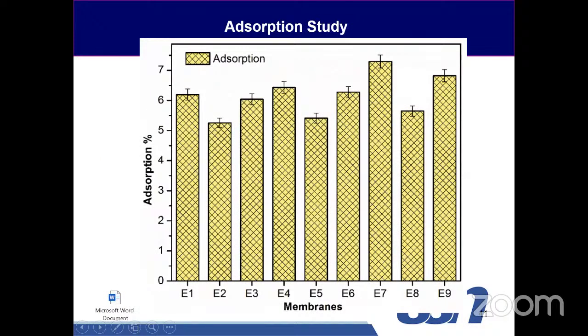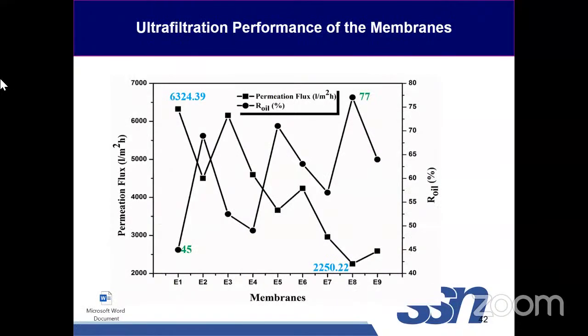Later on, we checked the ultrafiltration property of the membrane using an oil-water separation technique, where we found out E1 was the highest in case of permeate flux, and E8 was less. Since the fiber size is less and the packing density is more, the E8 membrane showed lesser permeate flux, but on the contrary, it has 77% oil-water separation, whereas E1 showed 45% filtration efficiency in case of ultrafiltration testing.